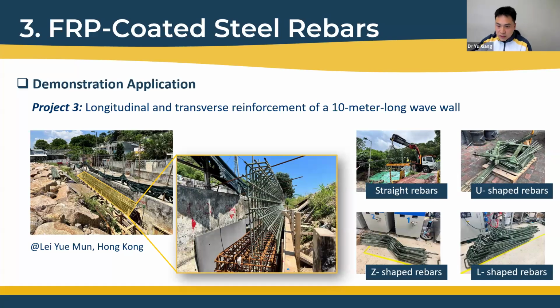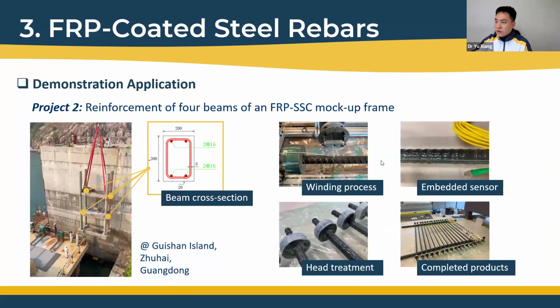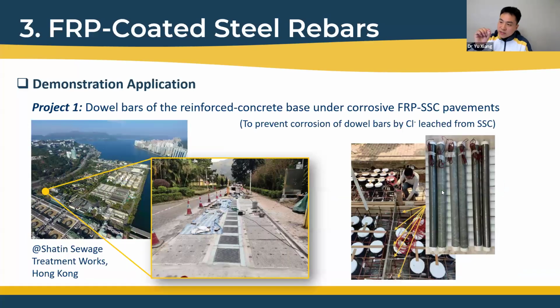The second point is when the coating layer is exposed to water containing alkaline and other things. I think this is a good point we are currently studying. As you know, the coating layer is not very thick, so I think this pH value issue will not just be governing for the FRP-coated rebar, because degradation will happen and the mechanical properties will be affected. So this is the issue we are currently considering.